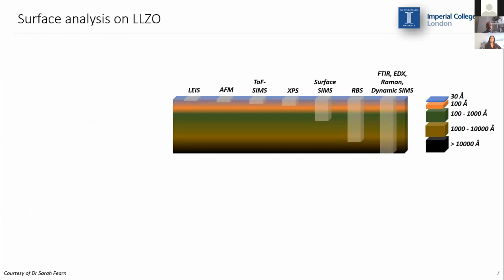To carry out surface analysis, we can use a wide range of surface analysis techniques. The Department of Materials at Imperial has a wide range of techniques available. We can, for instance, start from LEIS, low energy ion scattering, if we want to see the very top surface, the very first monatomic layer of a sample, and then we can use other techniques if we want to go deep into the sample, up to the bulk of the material.